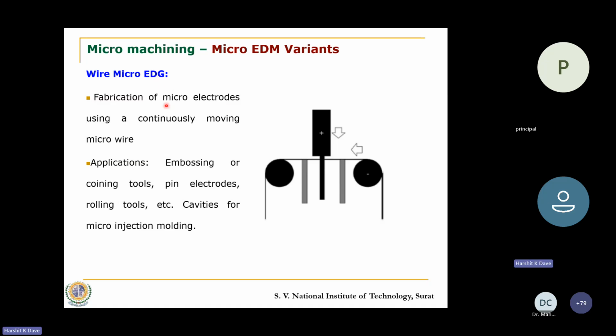This electro discharge grinding, when done with the wire EDM process, becomes the wire micro electro discharge grinding process. And here what you do is you are generating a micro size of tool. Initially, when we had the machine, we did not have tools other than 300 micron size of tungsten. So what we did was we made brass shafts up to 350 microns by micro turning, and then we put up this brass shaft over there, and with this wire, molybdenum wire, I think it was molybdenum or maybe brass, I don't recollect exactly. By moving this, we started reducing the size of this tool. It was continuously rotated, so it worked on the diameter, and we focused on reducing its diameter. So wire micro electro discharge grinding can be used for that purpose.